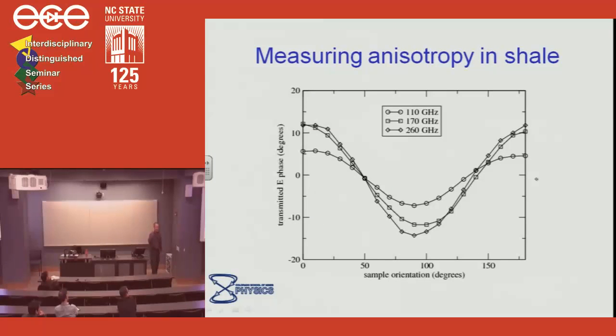Since we can easily measure the phase of the field, it's really easy to measure anisotropy. And so this is an anisotropic material. It's layered. The layering is actually caused by sedimentary deposition. And so it acts sort of like a diffraction grating. And as you rotate the thing in the beam, you can see this beautiful anisotropy that occurs at different frequencies. So from 110 to 260 gigahertz.